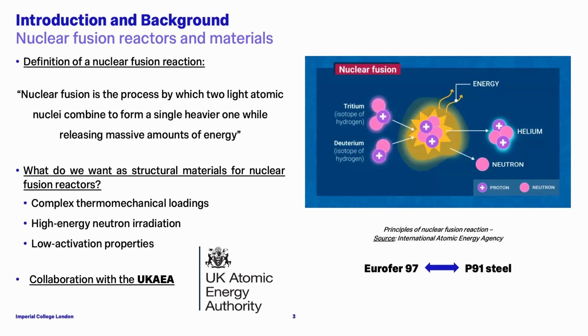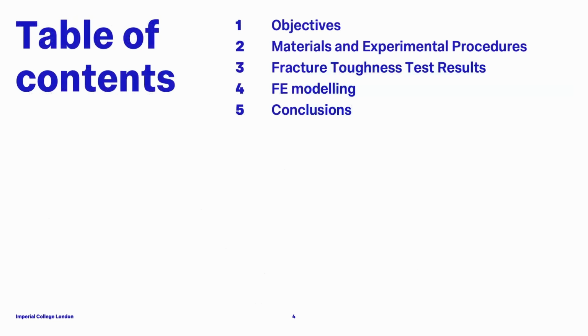And to do so, we need reactors. And to have reactors, we need some structural materials with some properties, such as being able to handle thermomechanical loadings or having low activation properties, for instance. My project is in partnership with the UK Atomic Energy Authority. And at the beginning, they wanted to focus on a material called Eurofer 97. But because this material is scarce, we did the test on P91 steel, which is quite a similar alloy with similar properties.